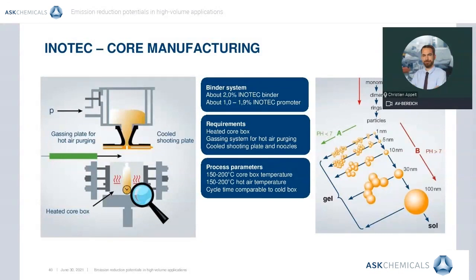The core production is characterized by a physical chemical curing mechanism. The introduction and supply of thermal energy from heated steel tools and dehumidified heated compressed air leads to the evaporation of the free solvent water and simultaneously initiates a chemical polycondensation reaction with the formation of a three-dimensional silicate network that describes the actual strength composite of the sand core.